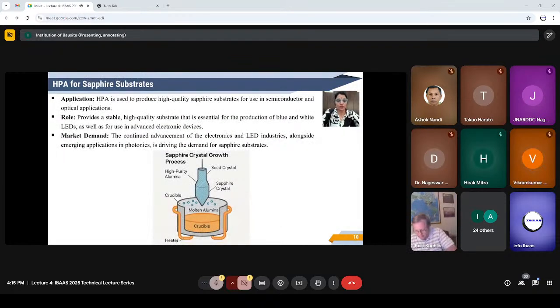So next is HPA's use for sapphire substrates. High purity alumina is actually the starting point for making a sapphire substrate, which are used a lot in LEDs and semiconductors. So what makes it so special is its high purity. Even a tiny amount of impurities, like I've talked about earlier, like iron or silica or sodium, can affect how the sapphire crystal forms. So we need 4N purity or even higher purity alumina, 5N or 6N, for making the sapphire.